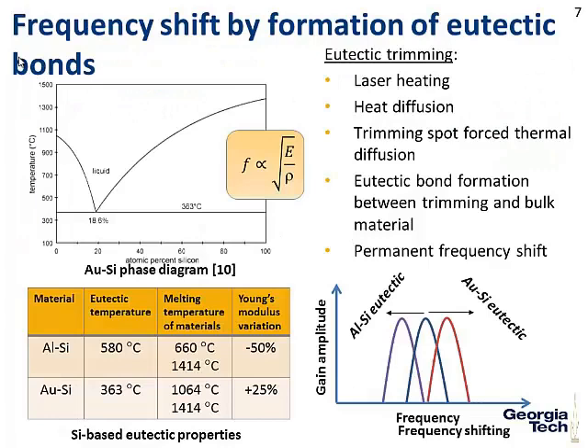So a bit about the physics behind it. What we're really using is called eutectics. For example, gold and silicon form a eutectic, and you see here its phase diagram. This is the melting temperature of gold, and here the melting temperature of silicon. As you can see, a given composition of the two is going to melt at a lower temperature than the melting temperature of gold and of silicon. So if you have your laser and you heat your device locally, if you're not touching your target location, you're not going to melt your silicon and you're not going to melt your gold, because their melting temperature is above that temperature.